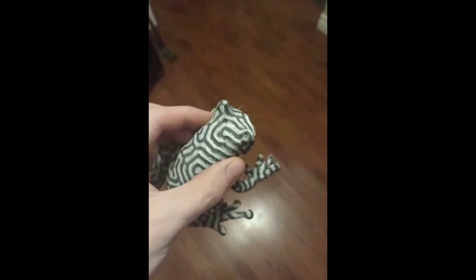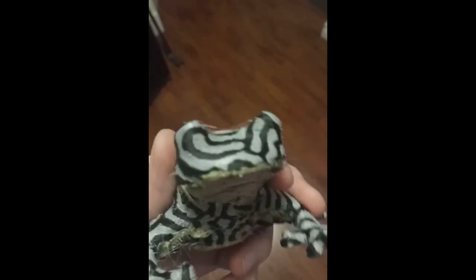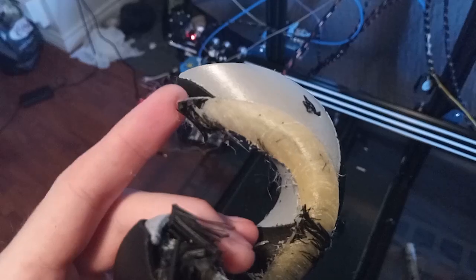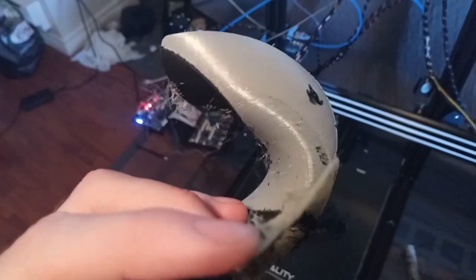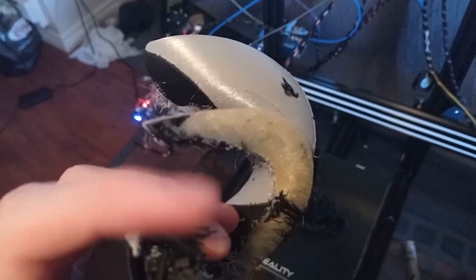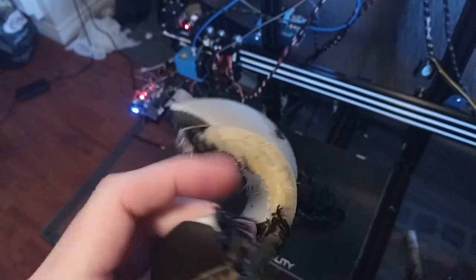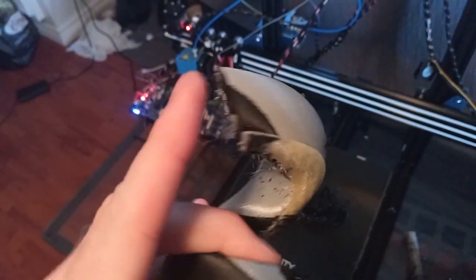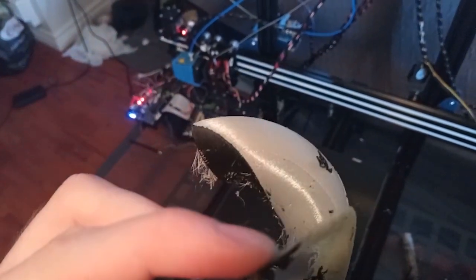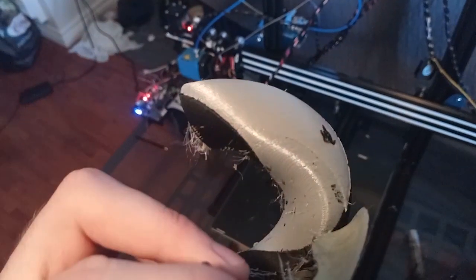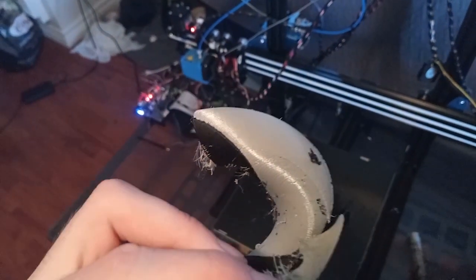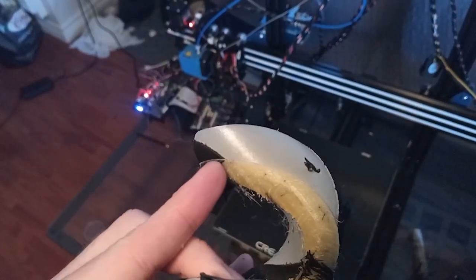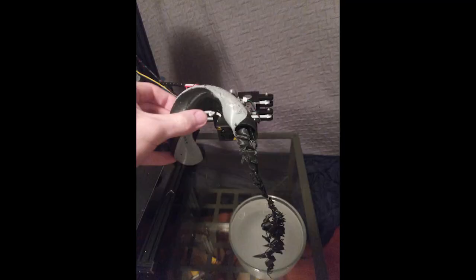We solved that problem by outfitting one of our nozzles with a dissolvable material called PVA, which is a material commonly found in school glue. This material can be printed like any other, and it is used as a support layer that allows us to print steep overhanging features with impeccable quality.